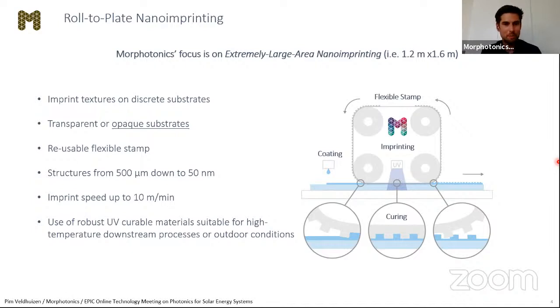We have a reusable flexible stamp that we employ, and this stamp can last usually over 1,000 imprint cycles. And the structures that we can print range from 500 micron down to 50 nanometers. So it's a very broad range. And the imprint speeds of up to 10 meter per minute ensure a high throughput. And we can work with highly robust UV curable materials that are able to withstand outdoor conditions. And on the right, you see a schematic of how the imprint machine will work.